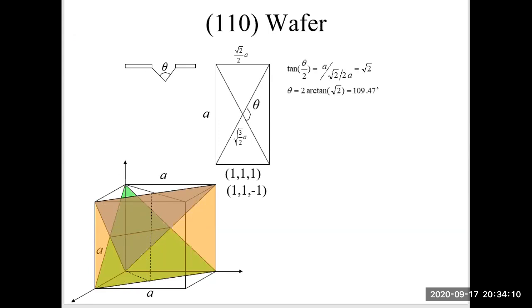Right. And this distance is a. This vertical distance is a, the length of the cubic edge. And this distance is half of the diagonal distance, so square root of 2 over 2 a. And these two lines represent the two 111 planes.